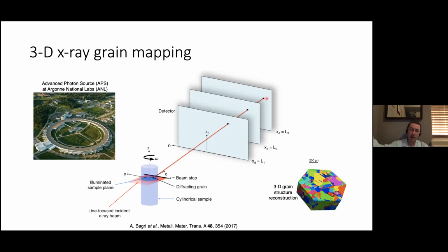And by extrapolating a line through the points at a given Bragg reflection, you can actually locate in 3D the location of the corresponding grain in the sample. And of course, you get lots and lots and lots of these spots. And so you have to somehow figure out the data analysis of how you're going to analyze all these diffraction images. That's really the main difficulty, the analysis of this kind of data. But once you've gone through the analysis, you get a 3D reconstruction of the grain structure.